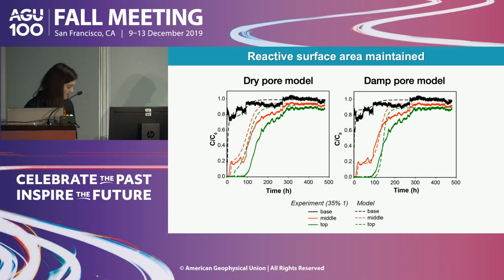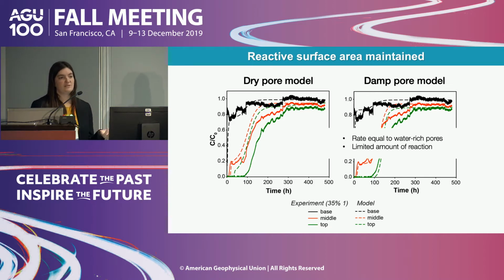And so what this suggests is that the reaction rates are not different in these low water environments compared to the water-rich regions. Rather, it's just the amount of reaction that's limited. So we can't react as much and we don't have as much water available. It sounds like sort of a subtle difference, but it's actually a pretty big difference in how we would approach modeling these systems. And you get quite a different result if you, for example, try and simulate a reduced amount of reaction by lowering your surface area, which is often what's done, but it would not work well in this case. And that's important if we're trying to model CO2 storage security, for example.